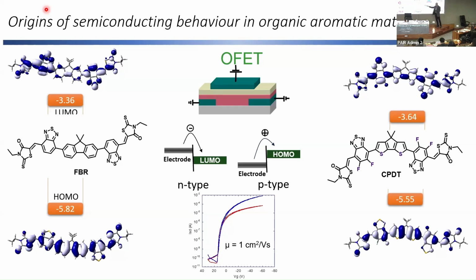You see the work function of the 2 electrodes is very different as well. So if you want to operate an electron transport transistor, you typically use a lower work function metal such as aluminium. If you want to operate a hole transport transistor, you'll use a very inert metal, a very large work function metal, gold or maybe even platinum, to be able to access this HOMO energy level.